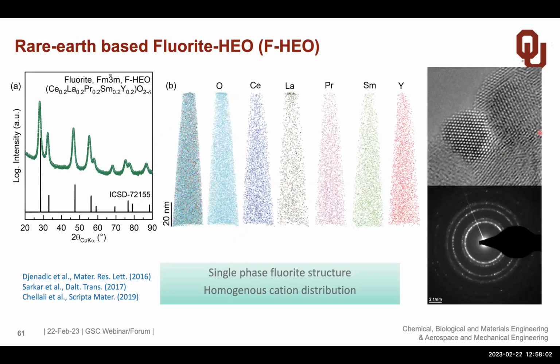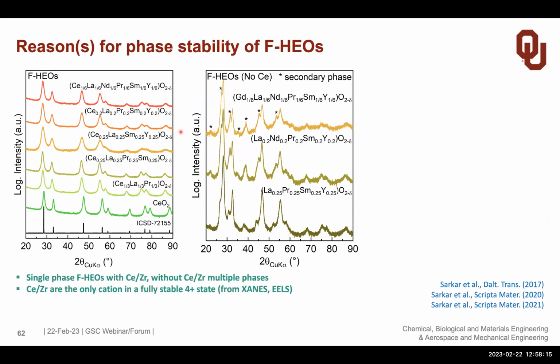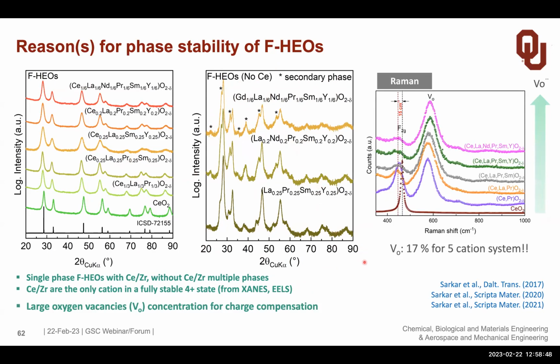And this is again showing the perfect crystallinity. It shows the single phase nature, and it also shows by this APT that we have a homogeneous cation distribution. It also shows that if you take one element out, the cerium, then the single phase nature disappears. And this is shown here. No cerium, we have secondary phases, which are shown here with the little stars. If you have cerium in it, we can basically go with any of the compositions and we obtain the fluorite structure and single phase. So the cerium here plays a very dominant role in the whole process.